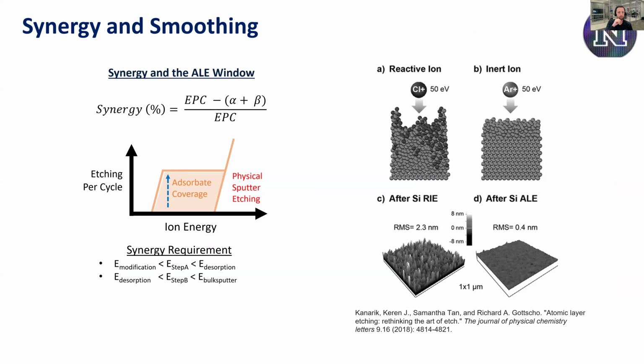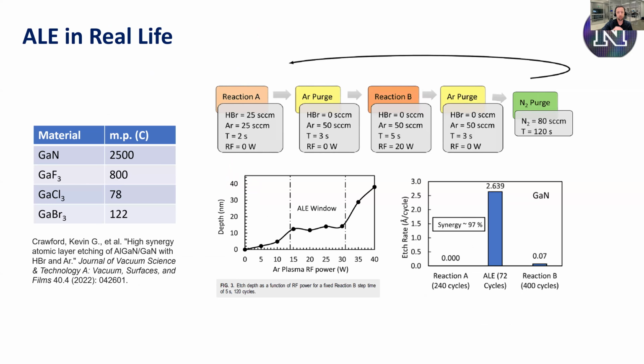Another example is work up in Glasgow on gallium nitride. Gallium nitride is pretty tough to just physically sputter. It's a pretty robust material. But if I can fluorinate it or chlorinate it or brominate it, that makes at least the gallium component much easier to remove. In this case, they're using HBr, and you can see that nice ALE window. At first, relatively little etch. Then once they have enough full coverage, there's a window where the etch rate is relatively constant. And then when they get above that, they start to get into a physical sputtering regime. They have very high synergy, and they also showed a really nice reduction in surface roughness. So that's ALE. Great. Okay.